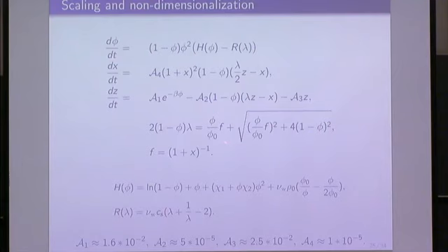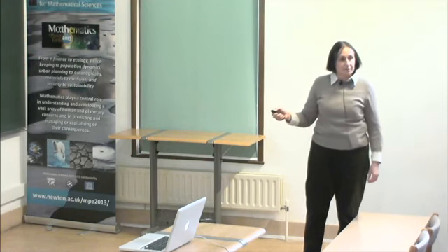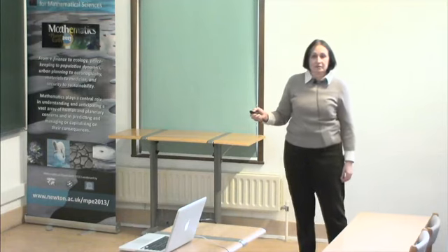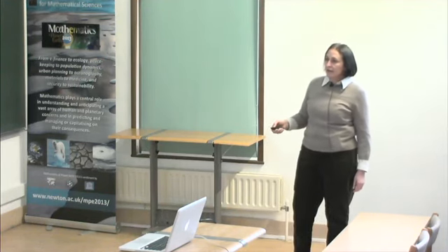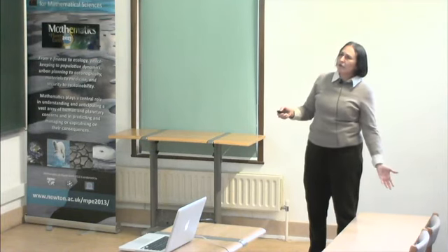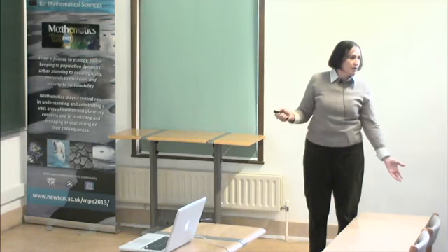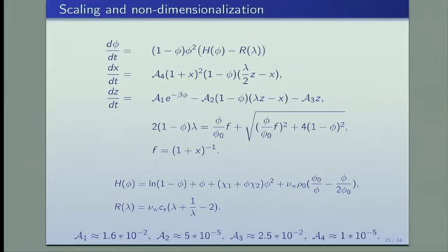So in a way this is the stress, actually the force. This is the part that comes from mechanics, elasticity plus Flory-Huggins. And this is the part that comes from the osmotic pressure, the pressure because of having ions. When I go to the typical numbers that the experiments work with, by the way, you don't see sodium, you don't see any other ones, because the concentrations are very small. So we have got rid of them.